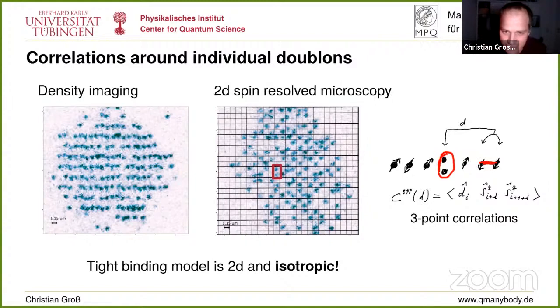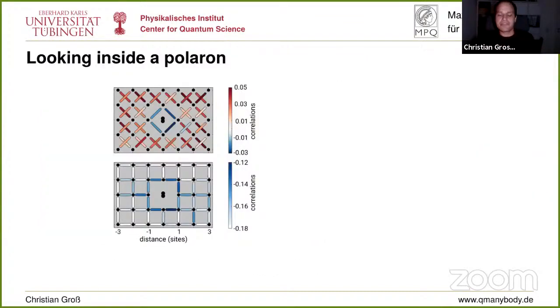And the whole rest of the talk will be about correlators like this. So it's important to understand these kind of correlators. It's about a combination of charge and spin correlators. And the distance that we use is the distance between where this charge sits and where the center of that spin correlator is. So this distance can be quite large, and we still have a nice spin correlation, even though the correlation length in the spin is short, because it is always a short distance spin correlator only involved in this. So this is important. So this distance might be 5 sites, whatever, but this is not a long range spin correlation we are talking about. Okay. So now we can use this correlator and analyze the system.